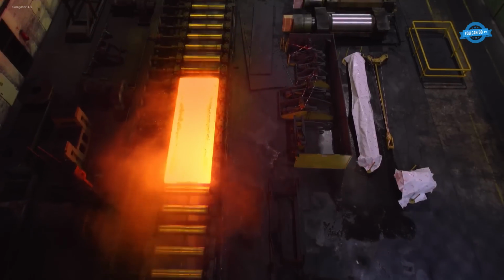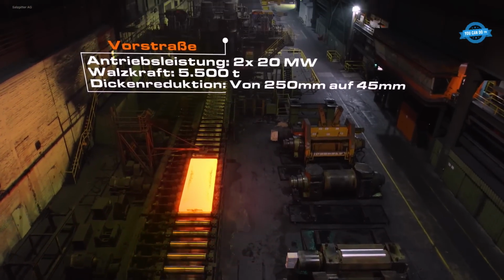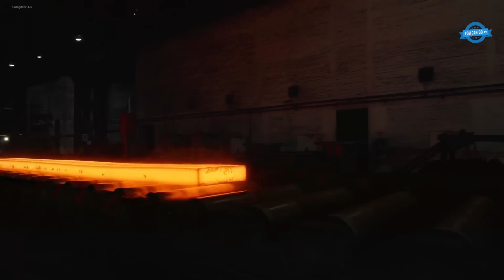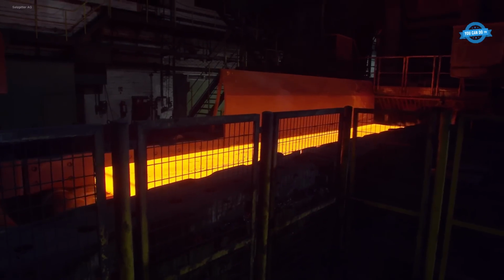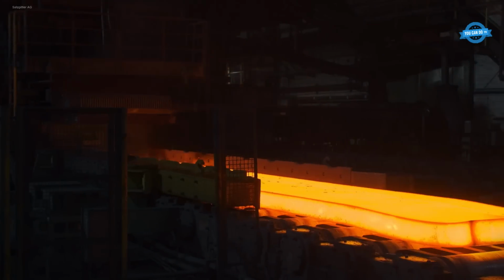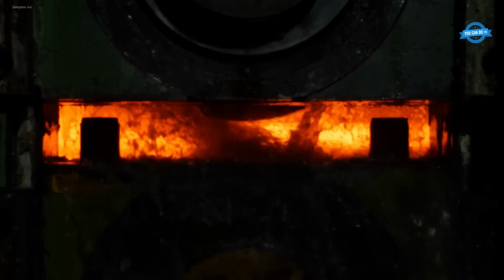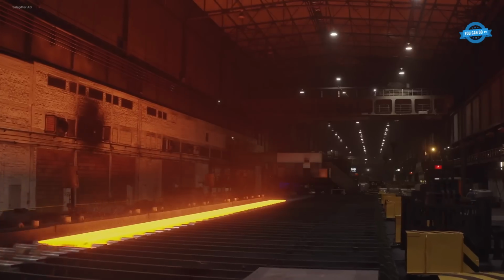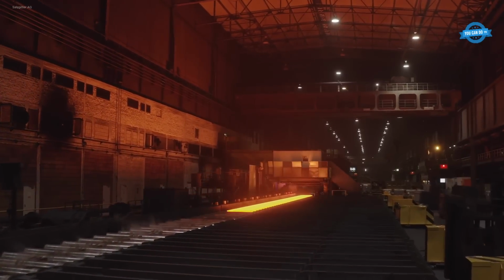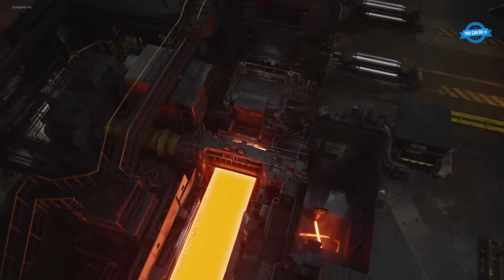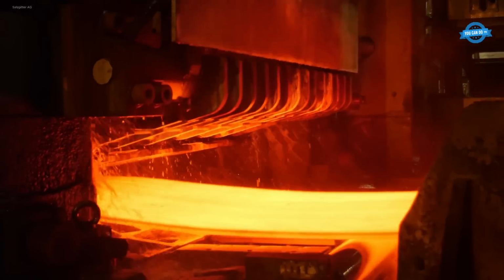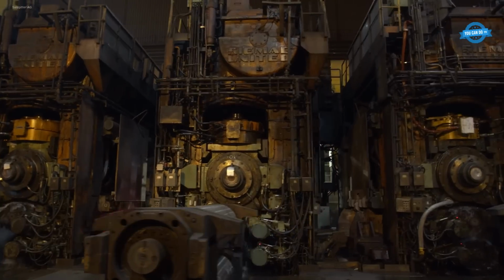In the roughing mill, twin 20 megawatts motors apply 5,500 tons of rolling force to reduce thickness from 250 millimeters to 45 millimeters. The finishing mill features stands rated at 30 megawatts each, over 40,000 horsepower, delivering final strip thicknesses from 25 millimeters down to just 1.5 millimeters and widths up to 2,020 millimeters.